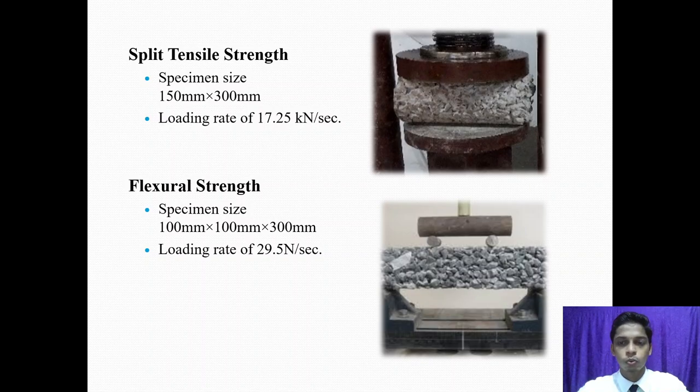To determine flexural strength, we conduct 2-point load test using 100 mm x 100 mm x 300 mm bar as per IS recommendation with a loading rate of 29.5 N per second. Load applied till the crack develops.